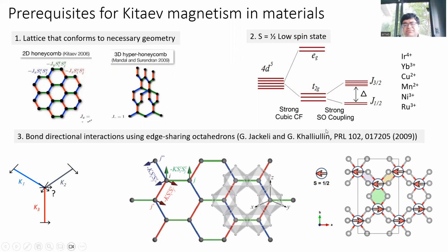And the recipe for that was given by the seminal paper by George Jackeli and Giniyat Khaliullin in 2009, where they figured out that if you have a honeycomb lattice of cations, which is surrounded by an octahedral cage of anions with a very strong spin orbit coupling on the cation, then what happens is that all the unnecessary Heisenberg interactions tend to cancel out, and you are just left with 3 Ising interactions on 3 bonds which face 3 different directions.